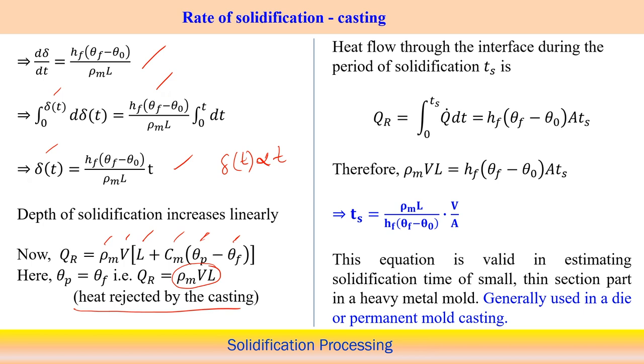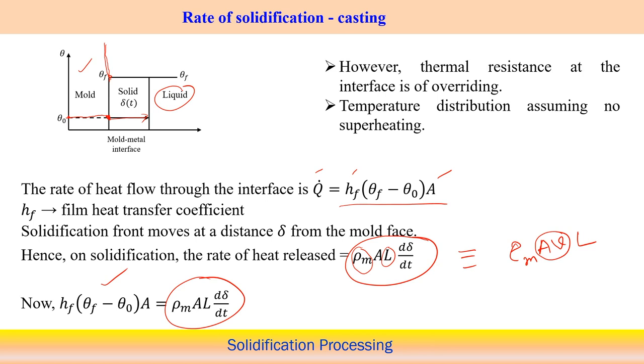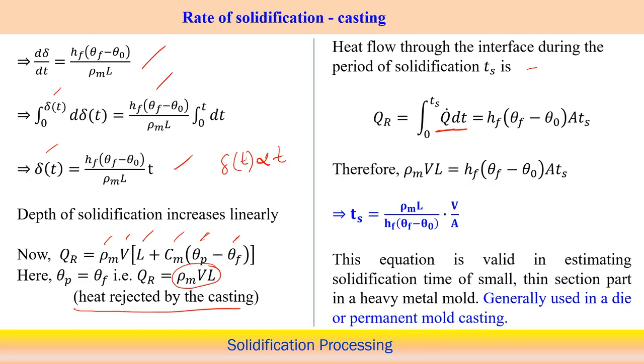Now, the same amount of heat has to be extracted through the interface. So we can calculate the other way: the total amount of heat flow through the interface during the solidification period T s. The rate of heat flow Q dot we have already seen: Q dot is h f (theta f minus theta 0) into A. So over the time T s, the heat flow is h f (theta f minus theta 0) into area into T s, where T s is the total solidification time.